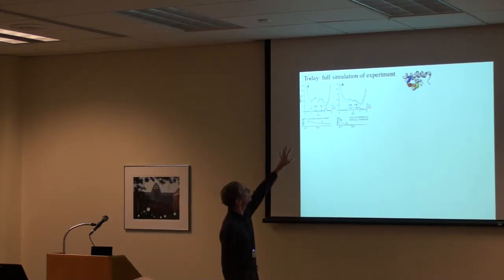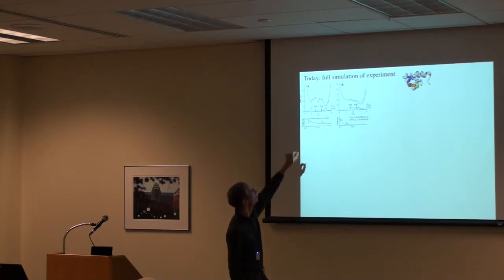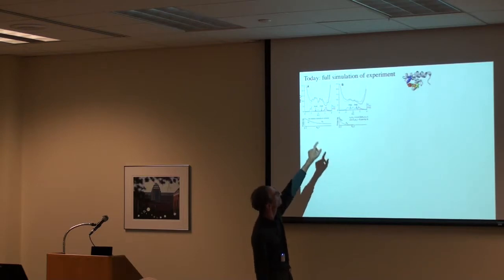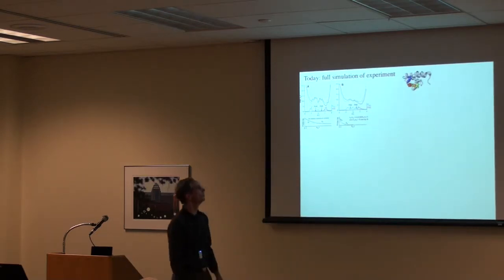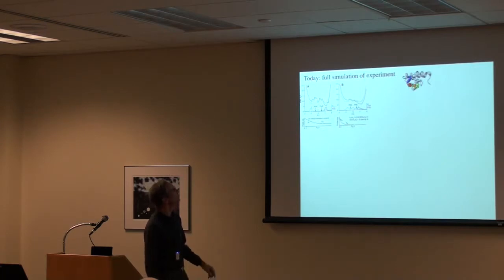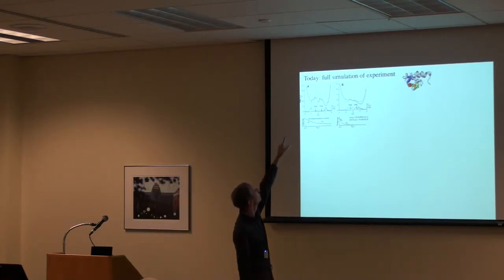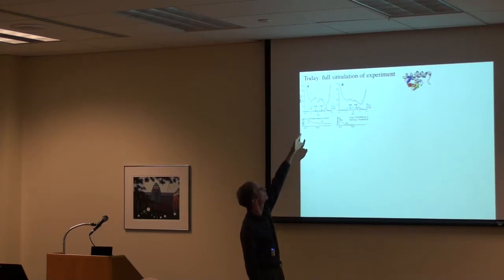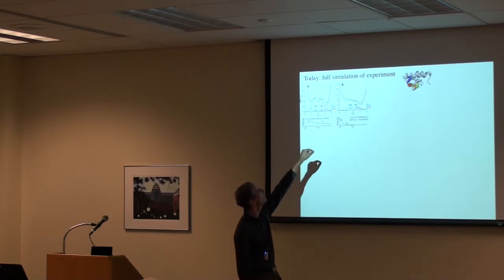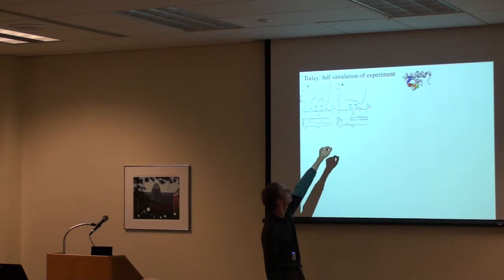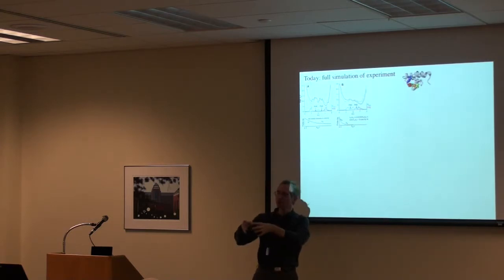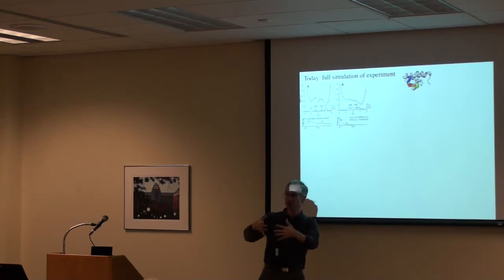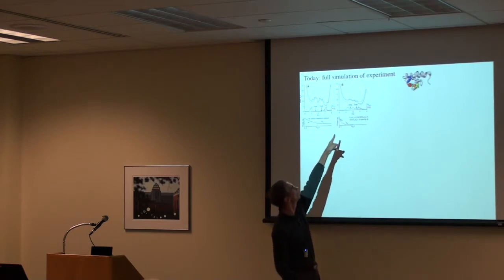And one of the questions is, when proteins get relatively small and very fast folding like this, are there still free energy barriers, like what's shown over in A here, versus does the free energy just go downhill from the unfolded state to the folded state, like what is shown on the right-hand side there? And in one of those cases, you expect that in the places where the transition states are, where you have a high free energy, the protein is not going to spend a lot of time there, so the probability of being there is pretty much close to zero. Whereas in the case where these barriers have essentially disappeared, the protein just goes through all these intermediate conformations with significant population probability, and you'll have a non-zero probability there.